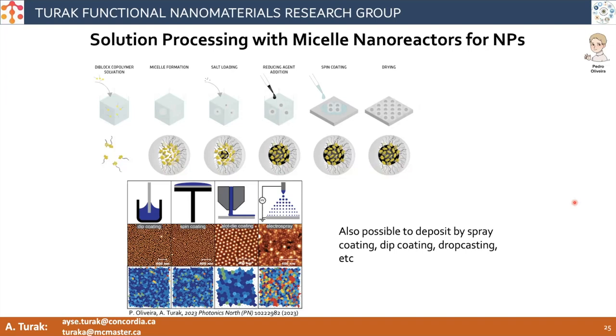But basically, it's agnostic to any of these techniques, and you can still get the same size particles because the particles are based upon the micelles themselves. And so as long as the micelles survive the process, whatever you get on the surface is going to be an array of particles. So again, they would tend to self-assemble into these hexagonal arrays. And there is an ability to tweak the pH, for example, or the nature of the solvent slightly to get different packing when it forms on a surface. It's possible to get square packings, different kinds of packing structures, but the most natural one is hexagonal, and so we often aim for that, for simplicity's sake. But it is basically agnostic.